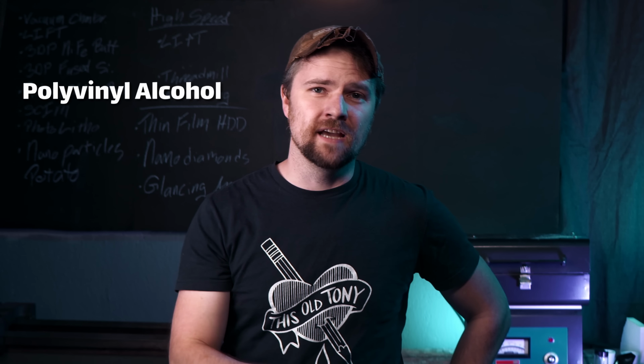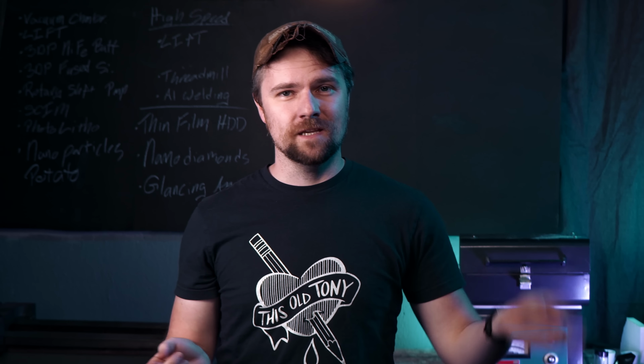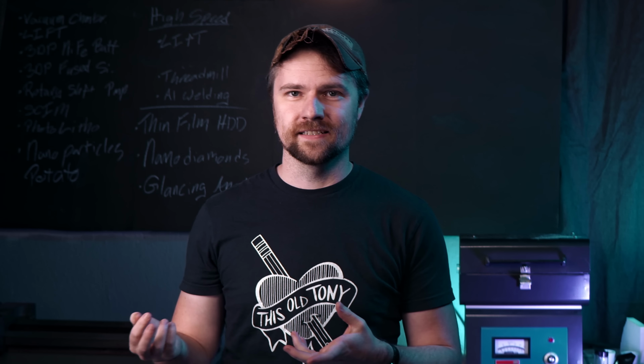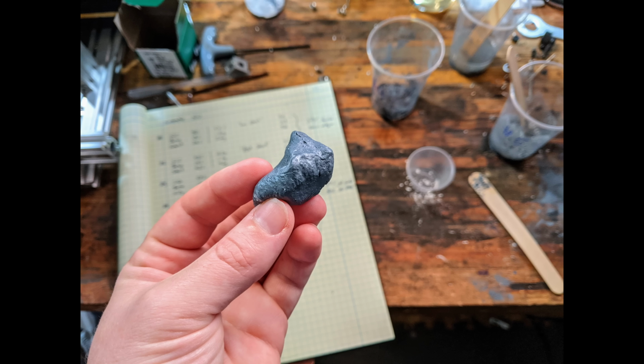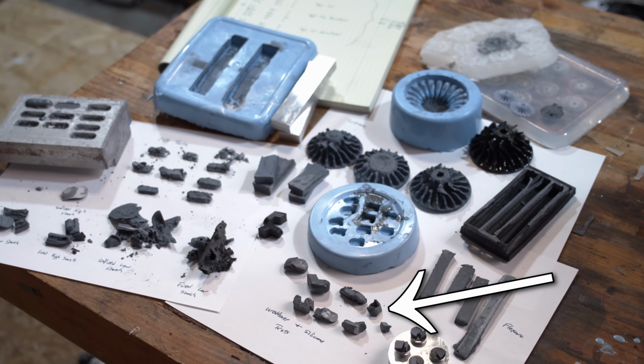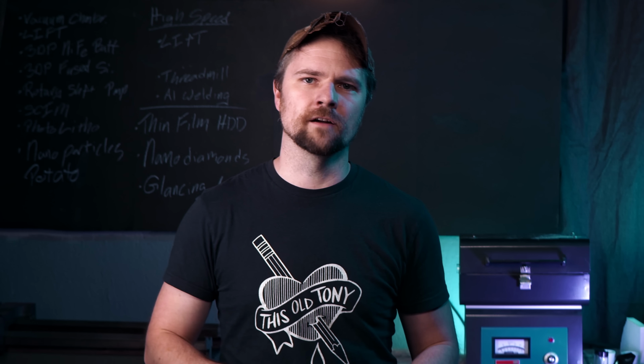There are a lot of different binders you can use, so I tried PVA just to see if that would be a little easier. But I actually didn't realize that when you mix PVA with borax, you make silly putty or oobleck or whatever you want to call it. It's a non-Newtonian fluid that instantly gels up when you mix the ingredients together. I also tried silicone, PDMS, as well as urethane, and both of them sort of work to different degrees, and it's something I would like to look into in the future, but I just went back to the paper and used starch and just accepted the long drying time.